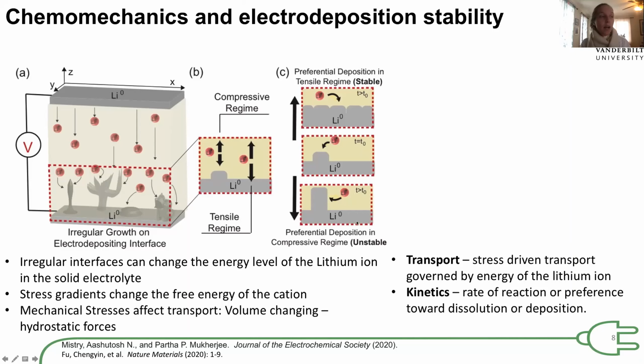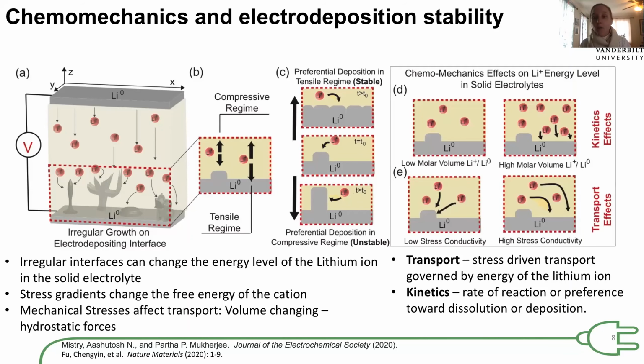And in this theoretical paper, it shows that this really comes down to a property of the solid electrolyte, in terms of tailoring the molar volume mismatch and therefore controlling the kinetics of deposition or dissolution, or changing the properties of the solid electrolyte in terms of the stress conductivity, whether a lithium ion prefers to plate out from a high energy state or compressive state to a tensile one, or vice versa. And so this gave us a platform for understanding how we can design electrolytes for both transport and kinetic properties for stable electrode deposition.